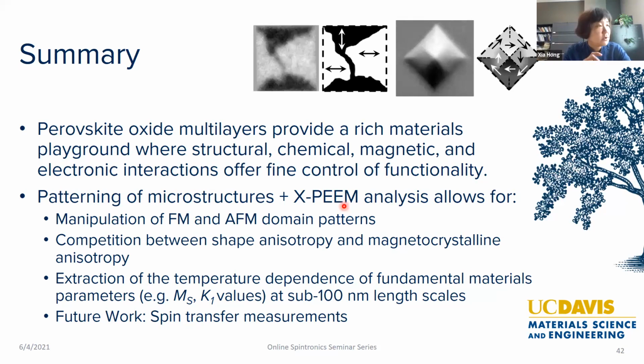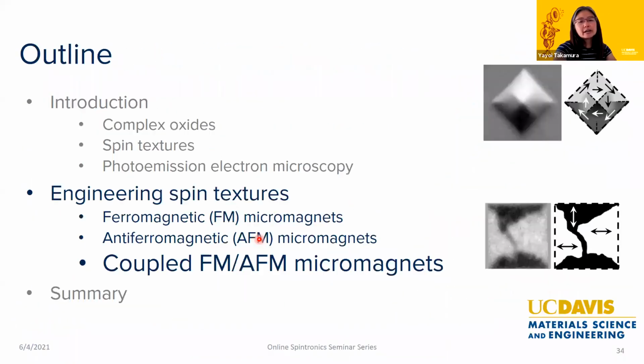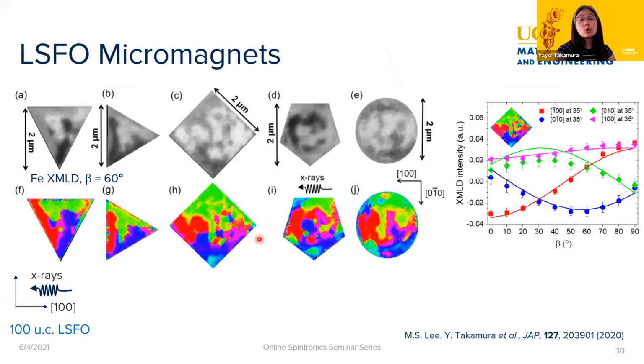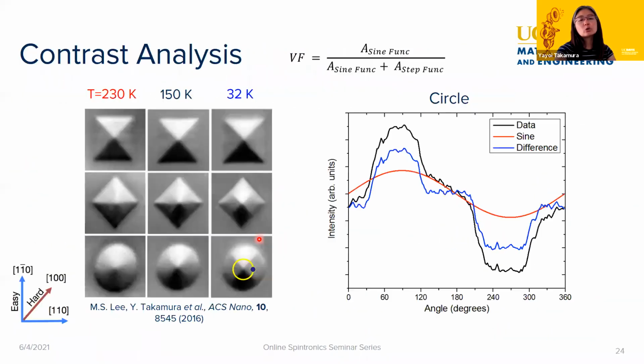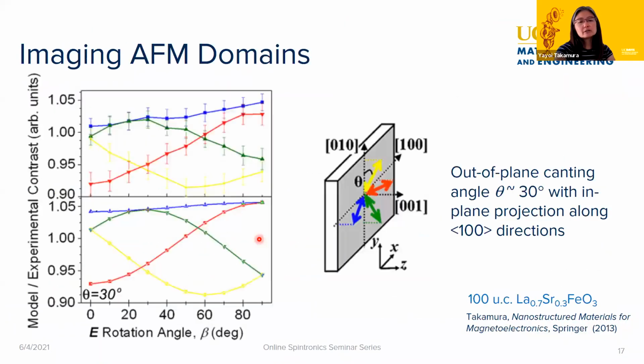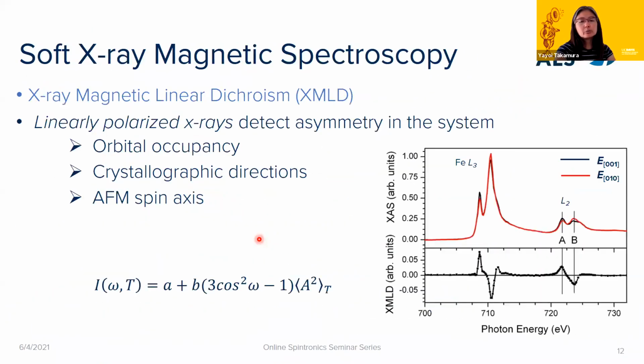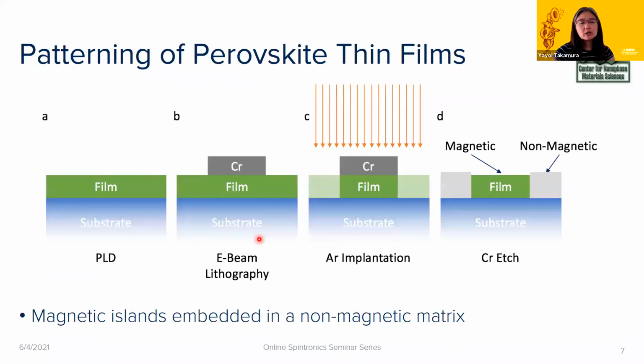You mentioned that you may make the top layer amorphous. Does that mean you need some protection, like a capping layer? That's what we did with the patterning. Yes, the way we pattern our films, our argon ion implantation is designed to amorphize the film locally. We put down a chromium hard mask, and the chromium hard mask protects the part of the film that we want to protect, and then everything else around it gets bombarded with the argon ions, and is amorphous and non-magnetic.